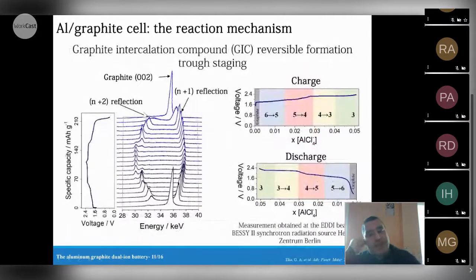The multi-staging process can be easily followed by operando XRD. This is a nice work done in cooperation with the research group at the Helmholtz-Institut in Berlin. You can clearly see that the 002 reflection of the graphite upon charge process splits, with the formation of two new reflections associated with the formation of the graphite intercalation compound through staging. And by following the evolution of the splitting of the graphite reflection, we can easily determine the staging behavior through the electrochemical process of charge and discharge.